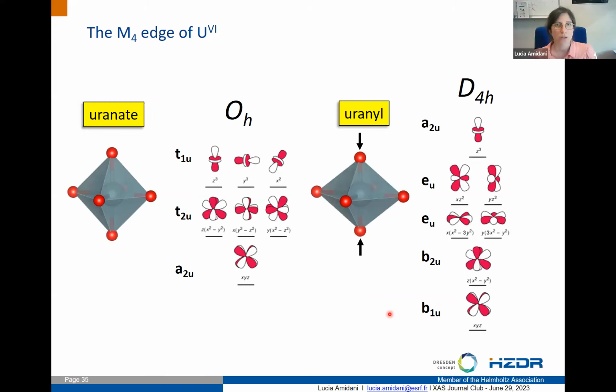What would group theory tell us about the splitting of the 5F shell in those cases? In the case of uranate, we expect the 5f orbitals to split into 3 groups: one single orbital pointing not towards the ligands, then the t1u group, and the t2u group, which is expected to be more destabilized by the presence of the ligands, because those F orbitals point towards the oxygen.